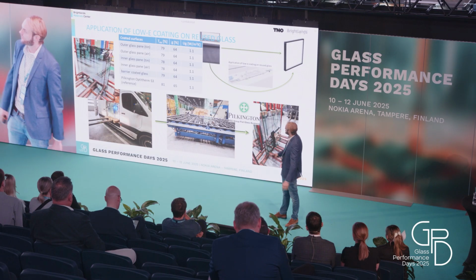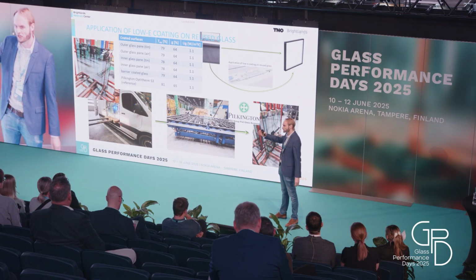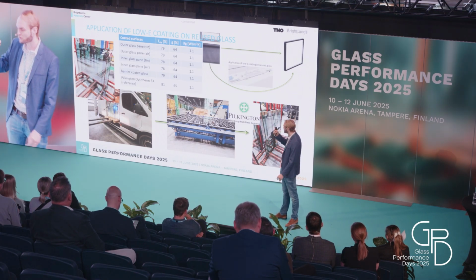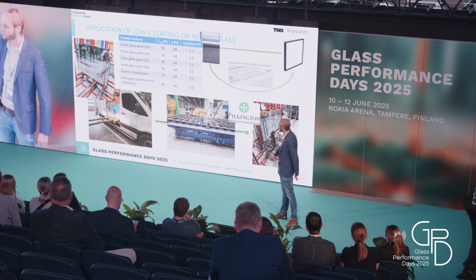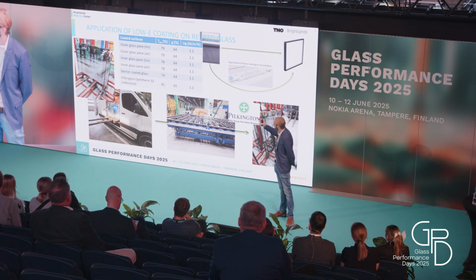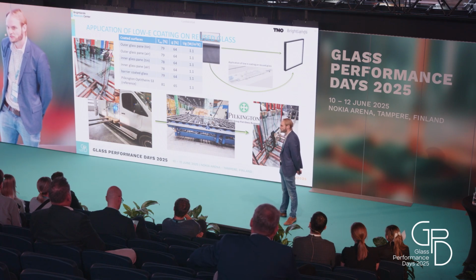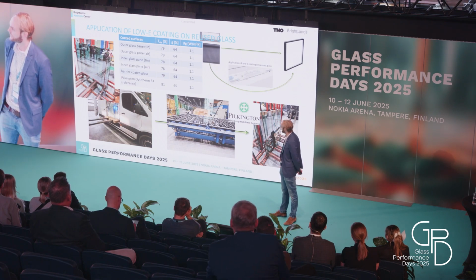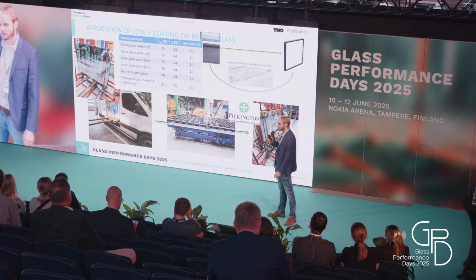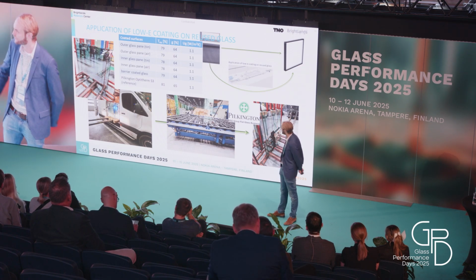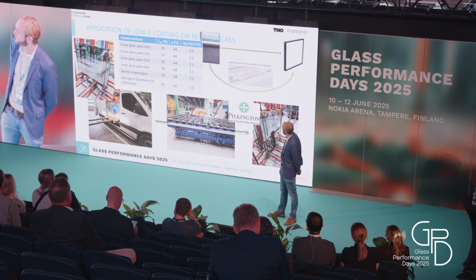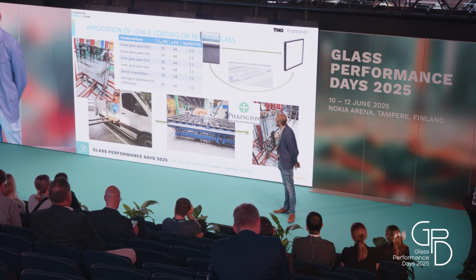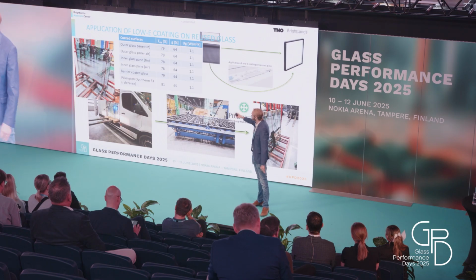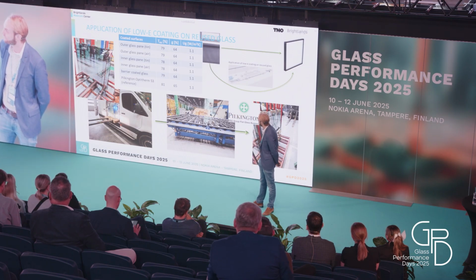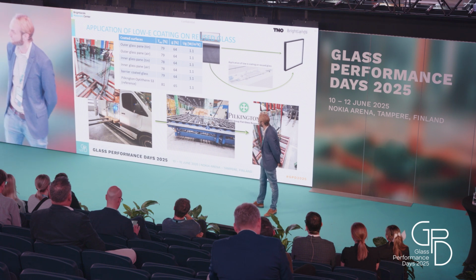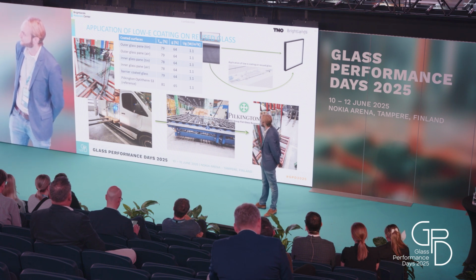Now you can think about, okay, there are different glass surfaces. You have the outer glass surface, the inner glass surface. You have the glass surfaces which were in contact with the inner part of the IGU. You have the tin side, you have the air side. Are there differences? Can all these sides be coated with a low-E coating? We also applied on some of the glass panes a barrier coating because we thought maybe we can refurbish the glass surface like that and make it easier to apply a low-E coating. The positive result here actually was that for all of these surfaces, we could apply the Optitherm S3 coating, and we had very good properties which are very in line with the reference Optitherm S3 coating on fresh glass.